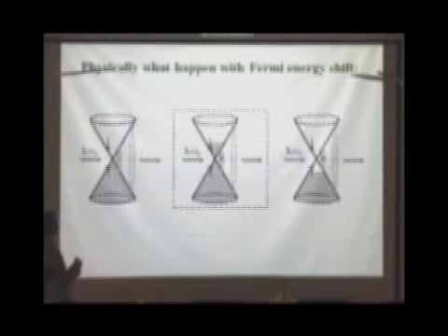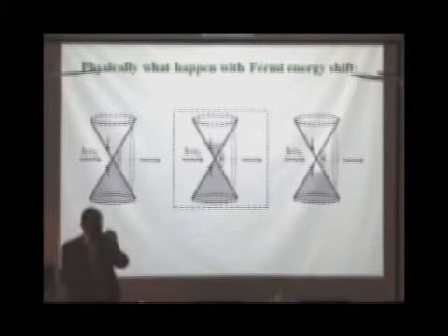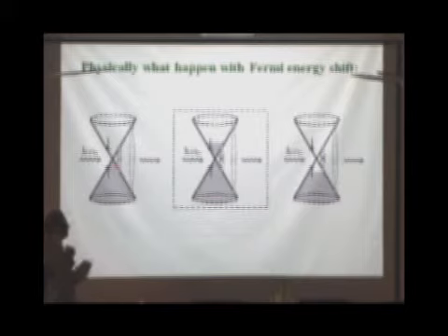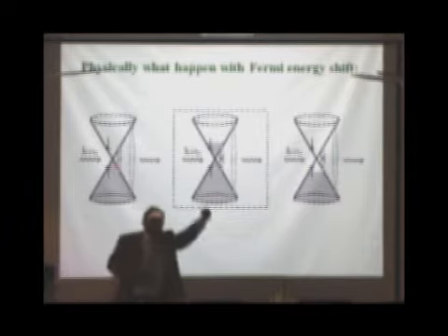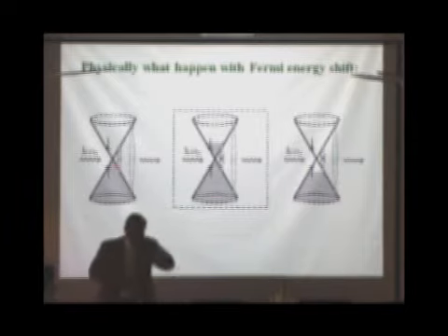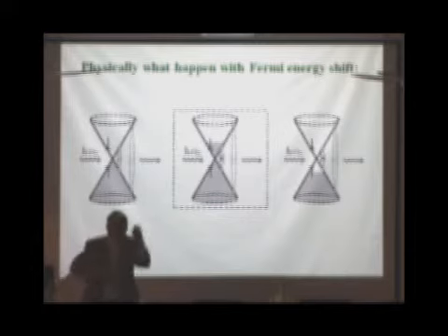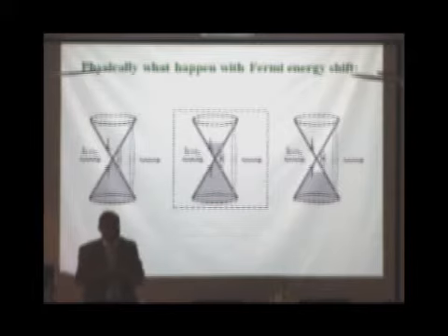So the idea is that if you have a band structure, these are all electrons filled to the valence band, no electrons here. Now what quantum mechanically, physically, you are doing: a phonon is able to make a transition across the valence band to the conduction band. This action leads to the dressing up of a phonon. So the phonon frequency can change, phonon lifetime can change.